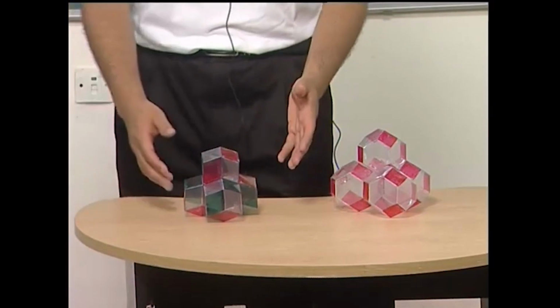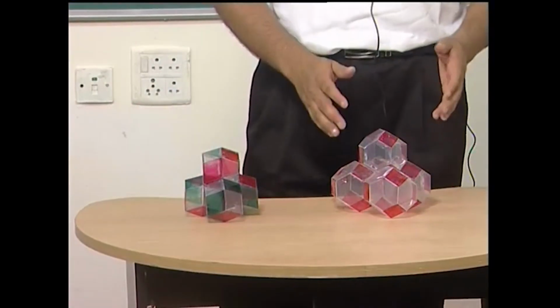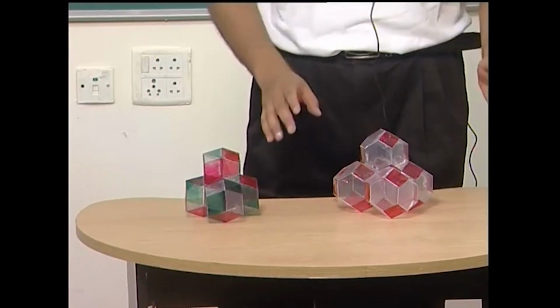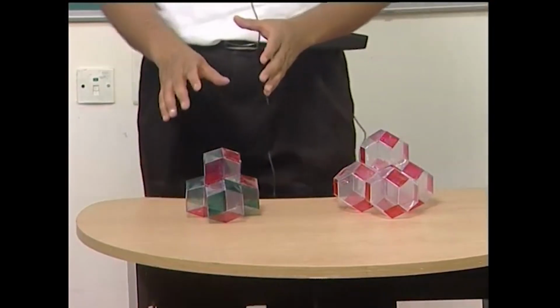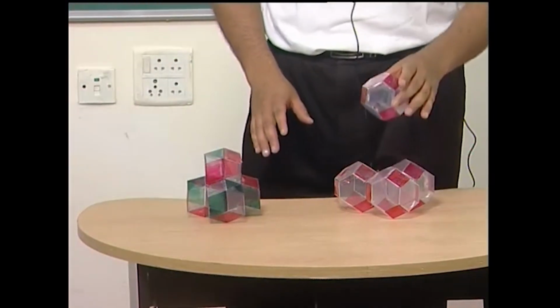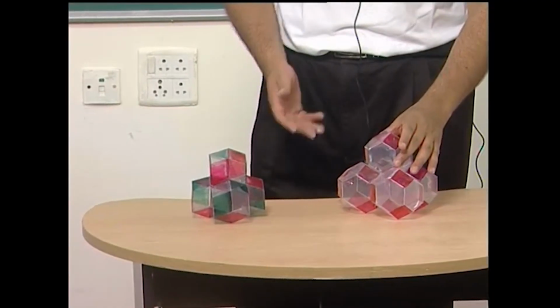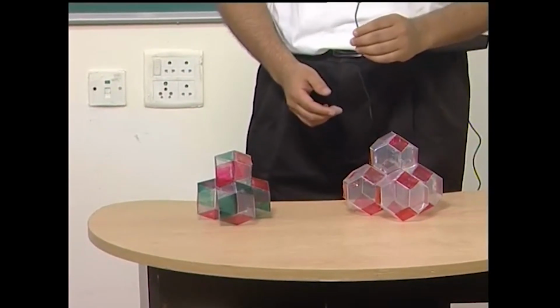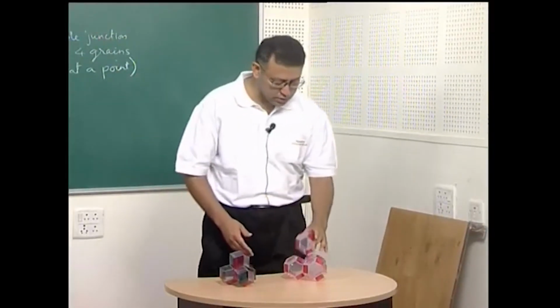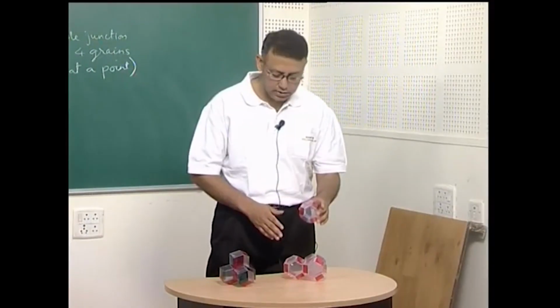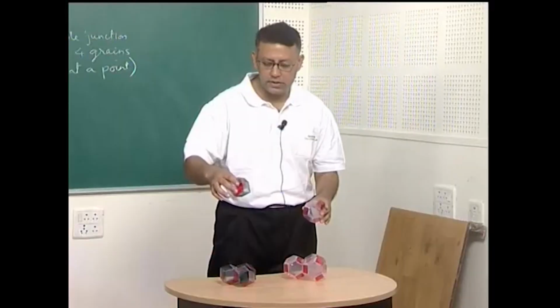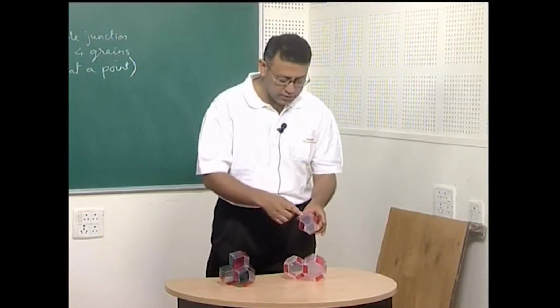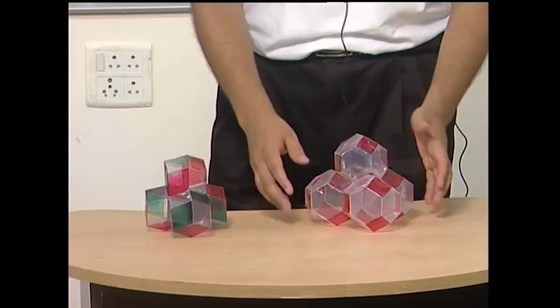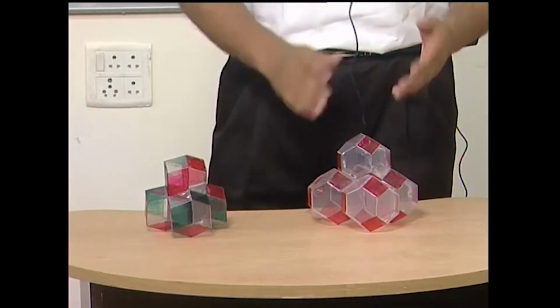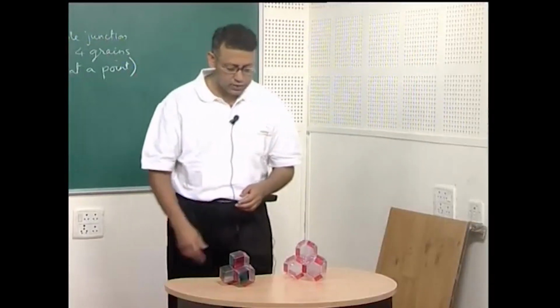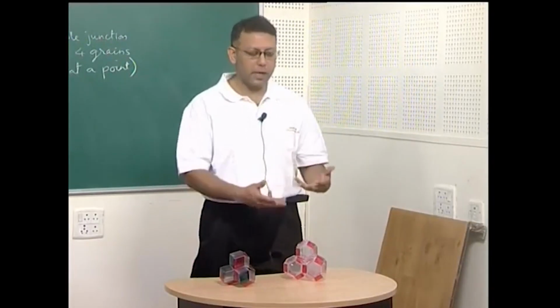Now, you can see how the rhombic dodecahedron and tetrakaidecahedron can fill space monohedrally, implying that a single tile, a single shape, can fill space. The reason for using these shapes is that it is mathematically easier to model. I have a single shape, and I can take the entire polycrystal to be made of grains of this shape. And the difference in choice comes because this solid, even though it is a preferred choice for a grain structure, some people also prefer to use a rhombic dodecahedron because every face has an identical shape, which is a rhombus. In this case, there are two types of faces, one is a hexagonal face and one is a square face, and therefore there are two choices which are classically used for modeling grains and to calculate effective properties from grain boundaries and also the mechanical behavior of grains.